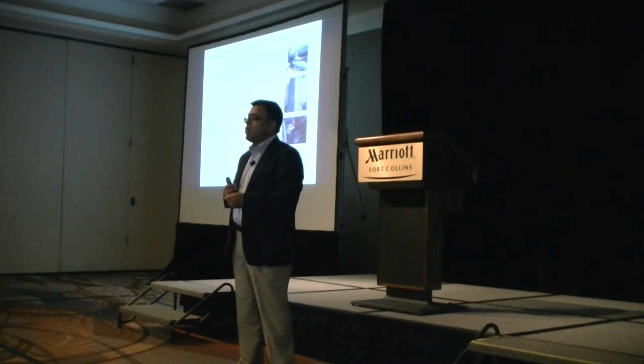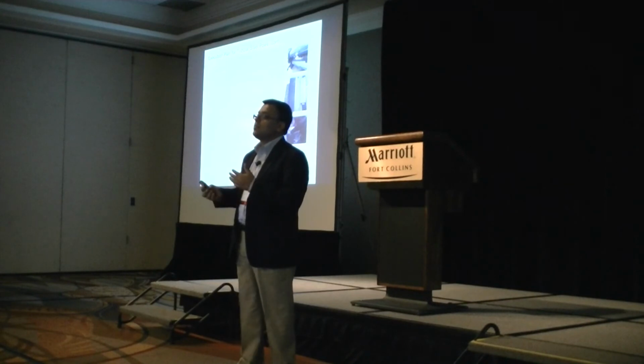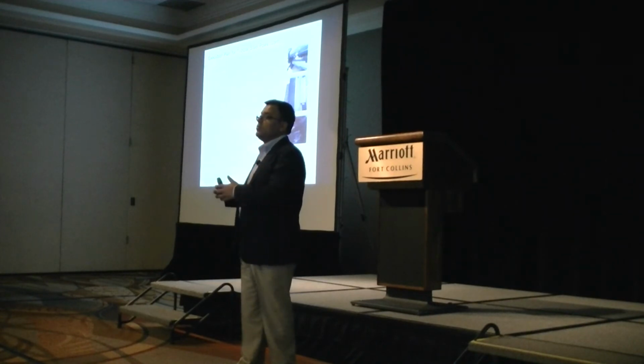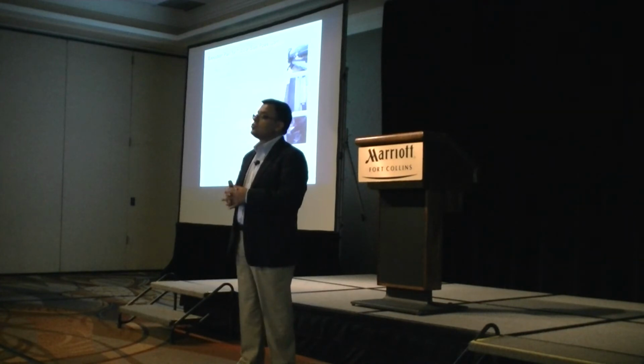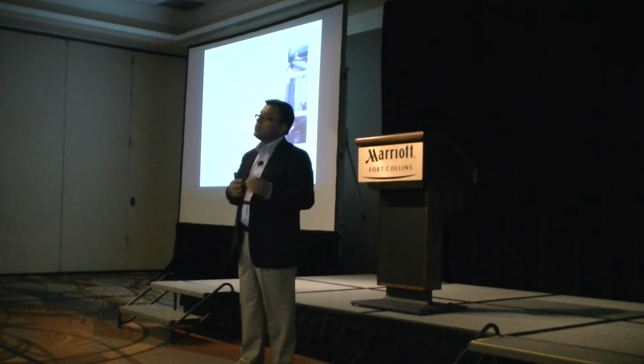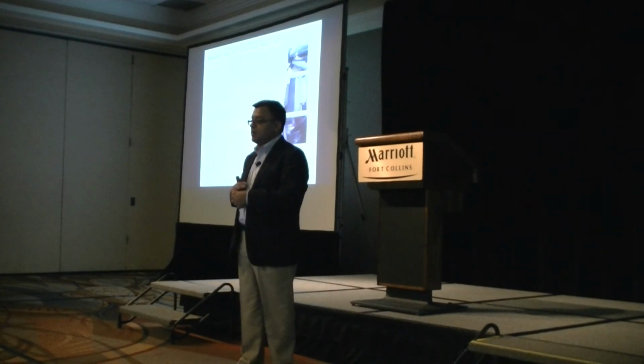The fit-up test, we also see a lot of issues with the fit-up test, especially in the splice joint. Sometimes you have a minimum, maximum, and a design splice. We recommend that you at least do a random fit-up test in the plant to make sure that you don't have any issue in the field. Also for the arm connection, if you have a critical arm connection where you need to avoid any issues, make sure that you do it sharp so that you don't have any problem there.